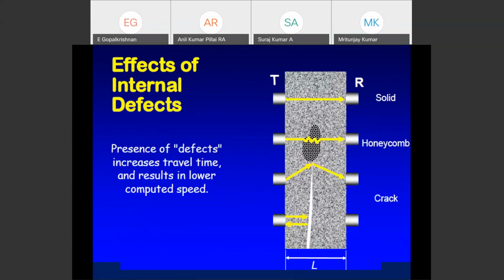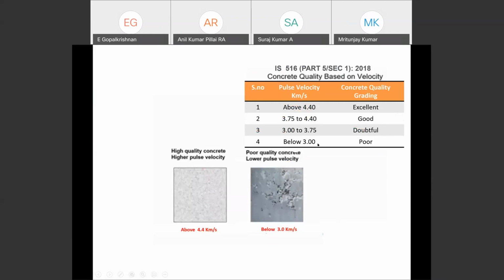The presence of defects increases the travel time, resulting in a lower computed speed. If honeycomb is there, the travel time is higher, so you will get a low velocity. When a crack is there, definitely it will not give any reading at all when the crack runs through. So we need to understand the defects through this testing. As per IS 516, the latest revised code, above 4.4 km per second is excellent, below 3 is poor. In high quality concrete, the surface is smooth and highly dense. It gives a high pulse velocity above 4.4 km per second. In poor quality concrete, where voids and honeycombs are there, it gives lower than 3.0 km per second, which is poor quality concrete, for example.